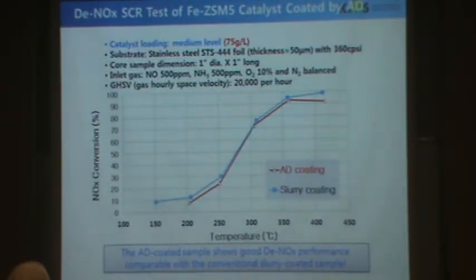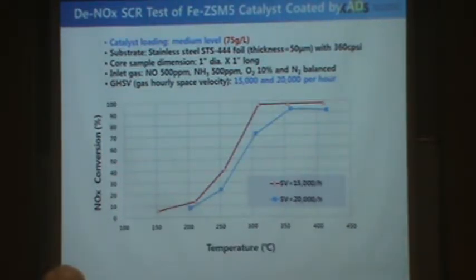We increased the level of loading to 75 grams per liter. And this one is our new sample, the AD coating sample. We didn't add any NO2. We just used the NO. The performance itself is not good, so you don't consider this absolute conversion. We just need to compare between the two samples. So we got very similar NOx performance. And we increased the space velocity, and it's very similar to the conventional catalyst.